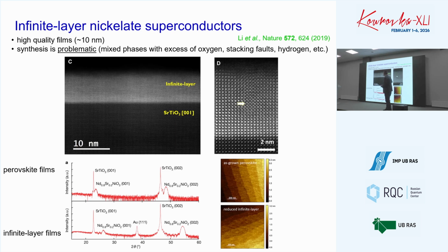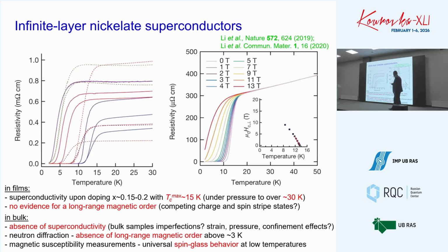This is an STM tunneling measurement along the z-axis, and they show some inclusions, completely different phases like either stacking faults or excess of oxygen. It's not that simple to remove all the apical oxygens from the system, from the perovskite phase. And the story about hydrogen is even more complex, because hydrogen is particularly difficult to detect in the crystal structure. But people managed to synthesize those materials, and it was surprising that from the